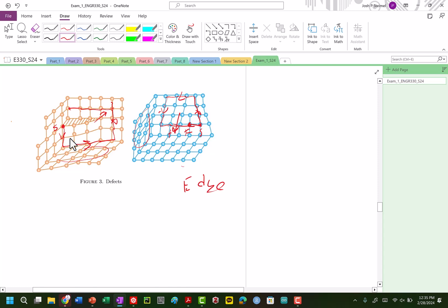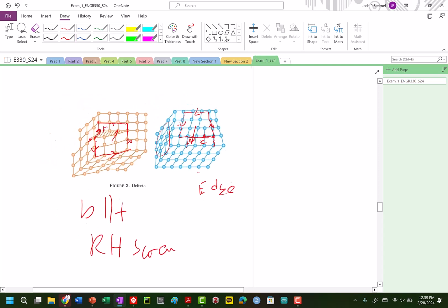Actually, hold on a second here. My counting is giving me consternation. So I'm going to go here. This is my start. 1, 2, 1, 2, 3, 1, 2, 3, 1, 2, 3. So there we go. I did 1, 2, I need one more. So that's my start. This is my finish. My start to finish. I was going out of the board for my tangent. So my Burgers vector is parallel to tangent, that's a right-hand screw. And they're all 1D defects. Fantastic.